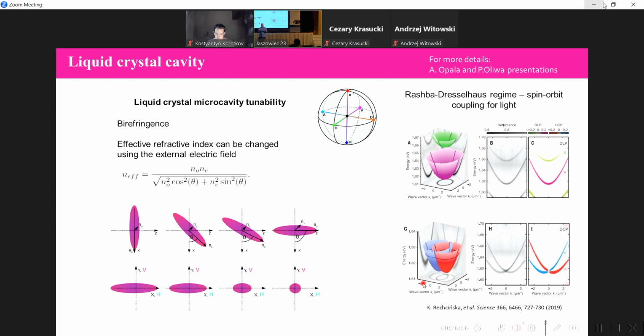And if we tune the mode with opposite parity, we obtain a situation where the light becomes circularly polarized with some splitting of circular polarization. This is called the Rashba-Dresselhaus effect, one way to realize spin-orbit coupling for light. If you want more details, there will be two other presentations on this effect in the same session, by Andrzej Opala and Przemek Oliwa.